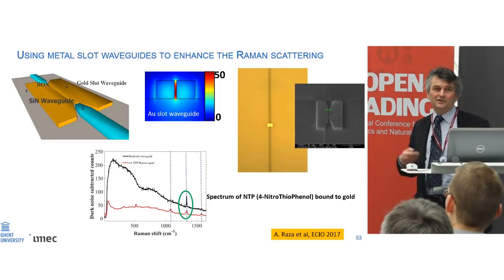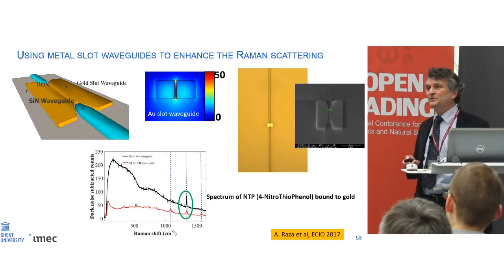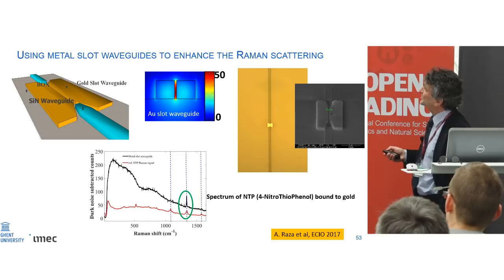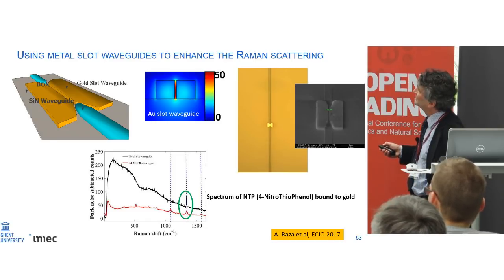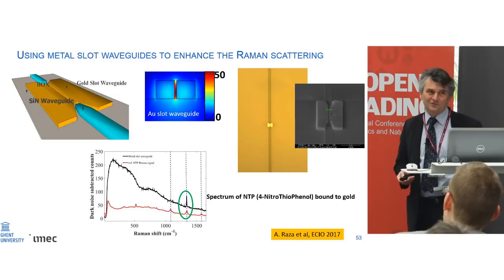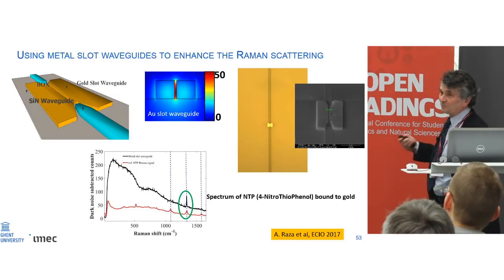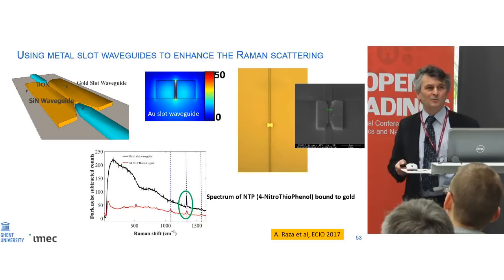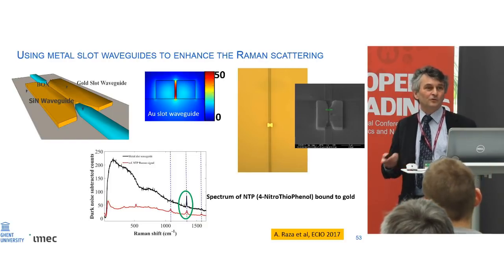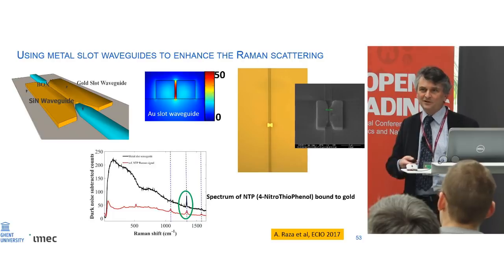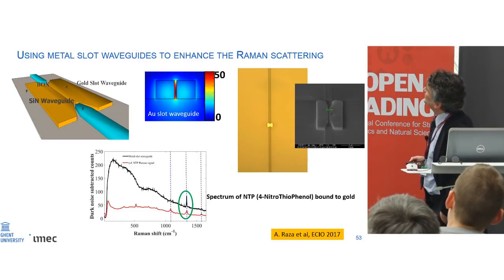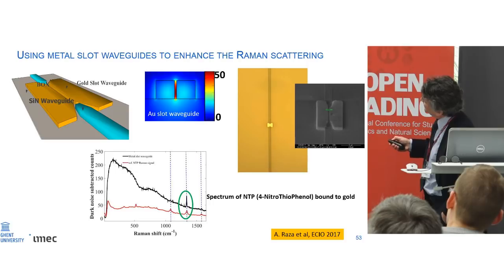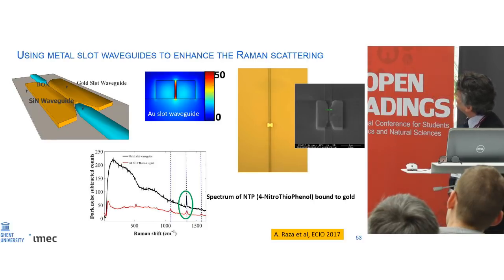And that is good because Raman, the intensity of the Stokes light in Raman spectroscopy scales with the fourth power of the electric field enhancement. So if you scale the electric field enhancement by a factor 100, then your Raman signal goes up by 8 orders of magnitude. So that's why we use plasmonics here. That's always the reason why many people in the world have been playing with so-called SERS, surface enhanced Raman spectroscopy, that's using the combination of plasmonics with Raman. Here we do this with this plasmonic slot waveguide, which we excite from a dielectric waveguide and then pick up the Stokes light again in a dielectric waveguide.